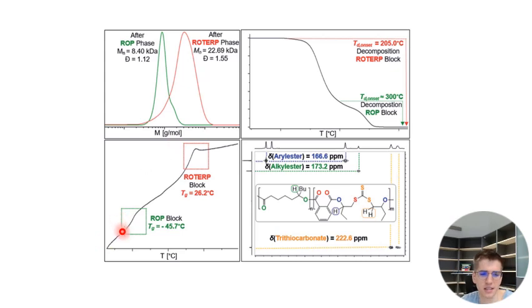But here just DSC showed us two glass transition temperatures, one around 30-ish degrees, which we determined before for just the isolated terpolymer. This was expected for that block, and for poly(epsilon-decalactone) it was known that it's around minus 50 degrees. Yeah, you see that they move a bit toward each other, right? Which is typical for block polymers, because they mix a bit and plasticize each other a bit, so they don't phase separate perfectly.